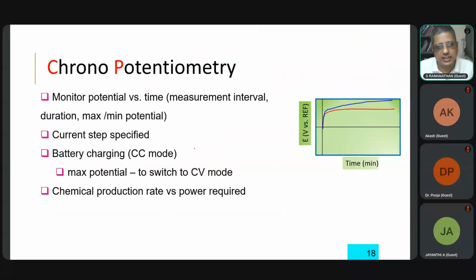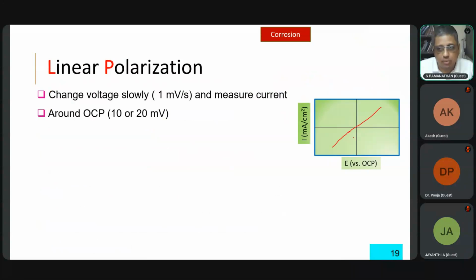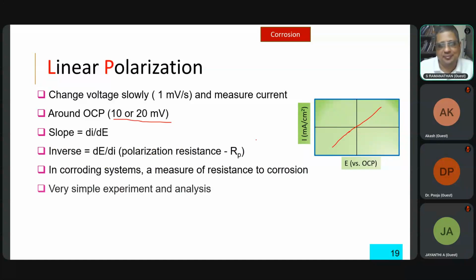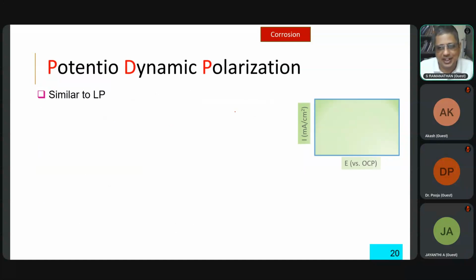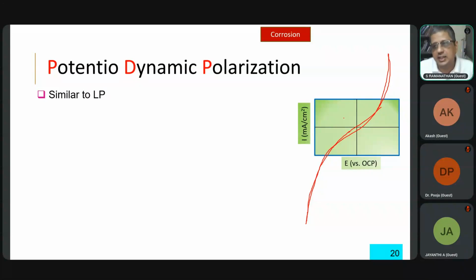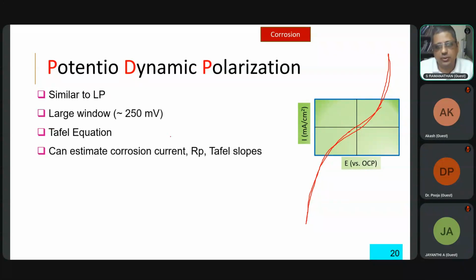Linear polarization is assuming it can be simplified as a straight line, and it is valid when you use 10 or 20 millivolt. If you use 50 millivolt, it will not be valid. On the other hand, if you use a larger potential window, in fact, I have used the same graph. I shouldn't have done it. It should look somewhat like this. Then I should fit the entire curve to that equation. If it fits reasonably well, then I can say this system can be modeled using Tafel polarization window, Tafel equation.